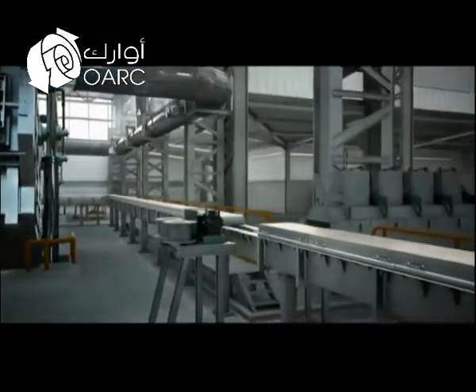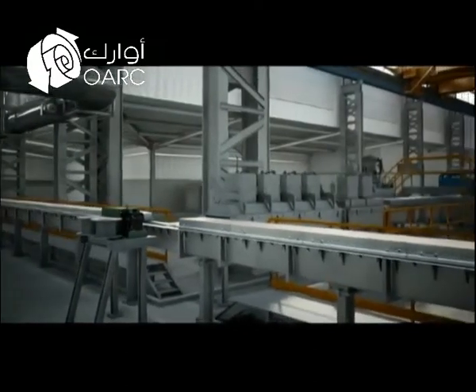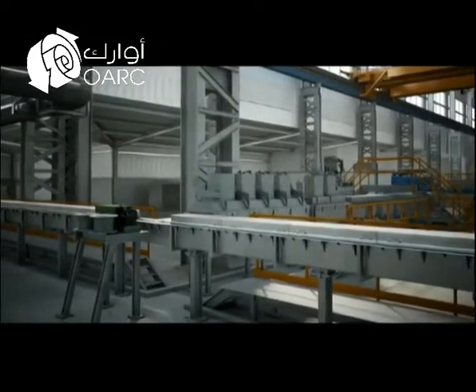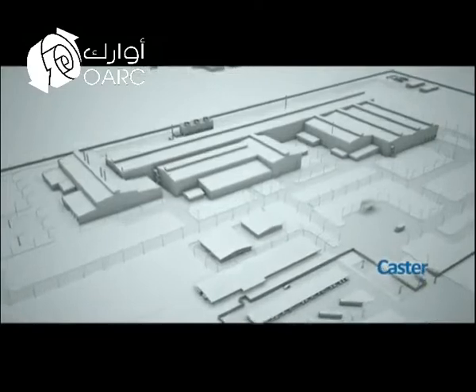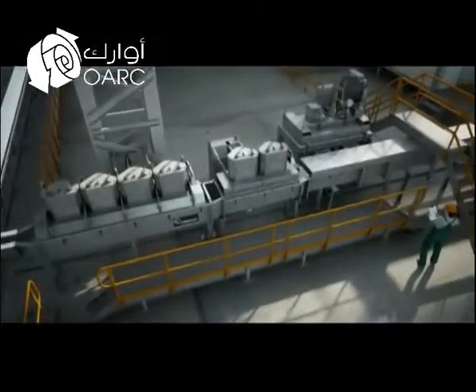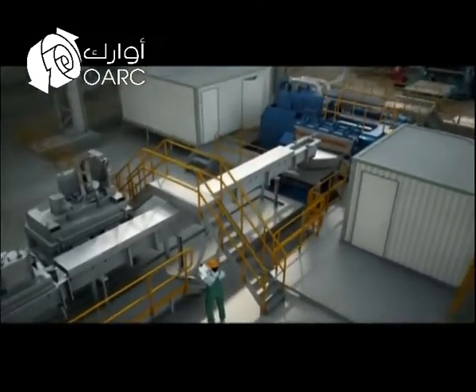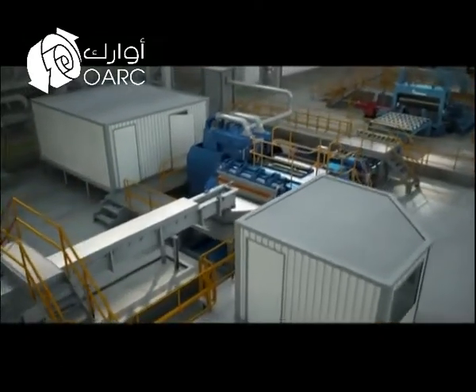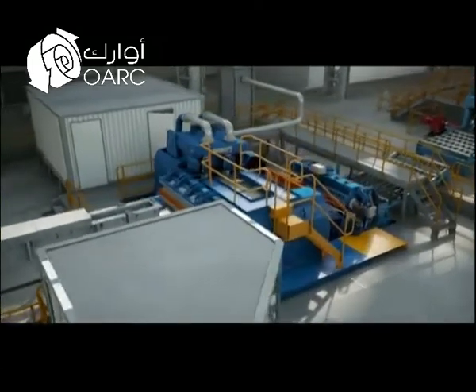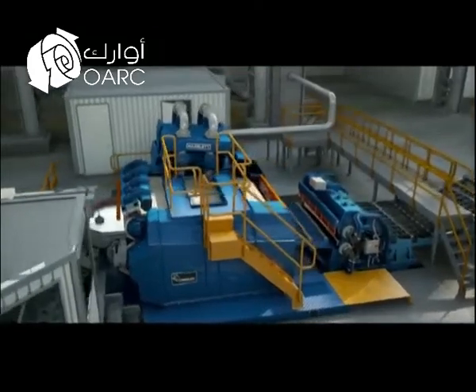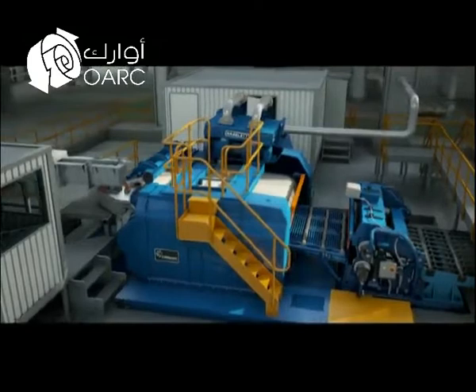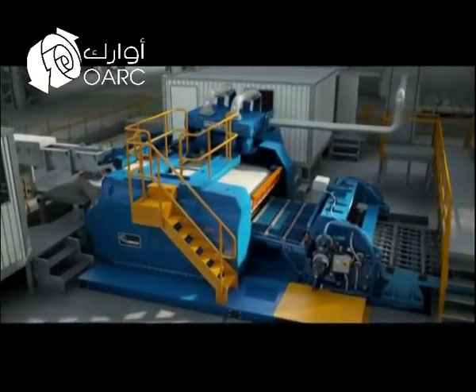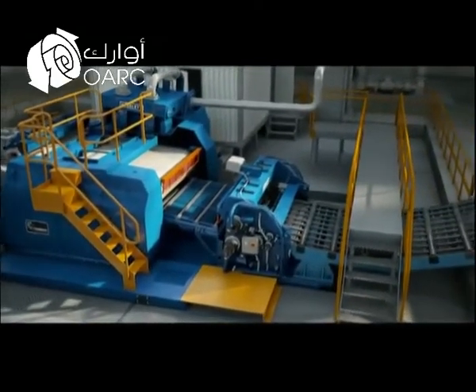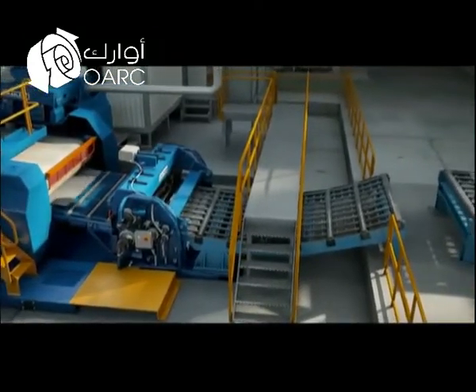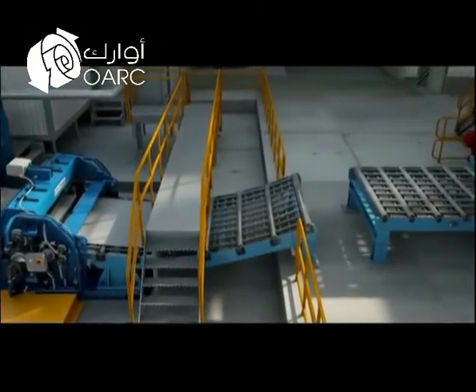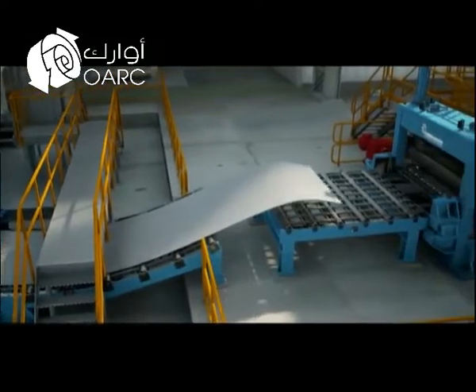To achieve the required quality at the caster, the molten metal is degassed and filtered along the line. Liquid metal is fed from the caster tundish between the 2 caster belts and solidifies in a continuous strip of metal. The sheet thickness will be either 16 millimeters or 19 millimeters, with maximum cast width of 2,032 millimeters and nominal casting rate of 51 tons per hour. Downstream, the caster pinch roll, the aluminium strip generates a natural loop that by gravity feeds the entry pinch roll of the hot rolling mill.